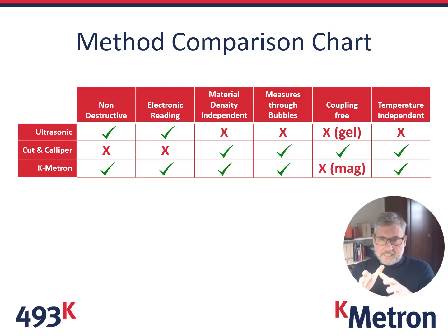The final one is an important one to include, and one we've had a lot of feedback on from our customers to say that one of the main reasons they move from ultrasonic to the induction method with the K-Metron is they have found that the ultrasonic system may give them a reading back, but it will be dependent upon the temperature of the polyethylene, the temperature of the part that they're measuring. So oftentimes molders, as soon as they demold the part, they want to know what the thickness of that part is before they begin again and continue to mold.